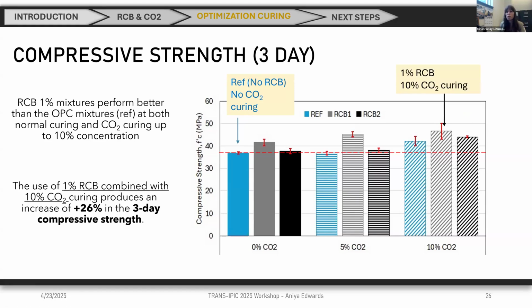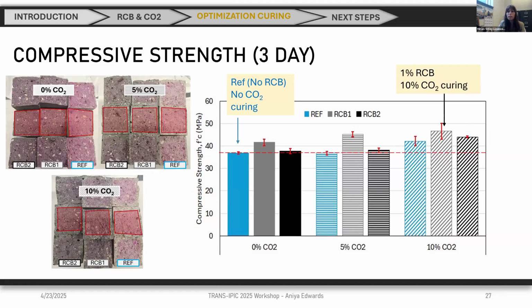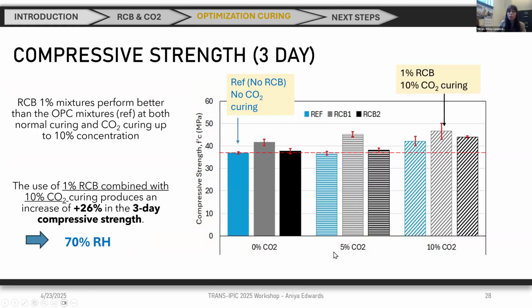And we are talking about a quite inexpensive way to increase quite a bit the early compressive strength, I will say. And this is not related to increasing the carbonation depth, because we can see that if we get, for example, the 10%, it doesn't matter if you're talking about the reference, 1% or 2%, we have very similar carbonation depth, and therefore an increase of the carbonation depth is not explaining this jump. But this is just some of the results with 70% relative humidity.